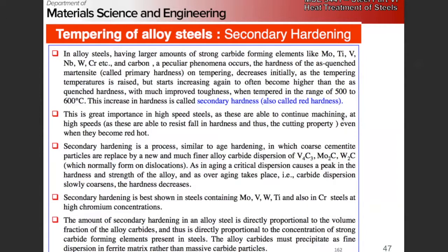So we take austenite, we get martensite? No. When you cool down, all of your austenite is going to change to martensite, provided you miss the nose, right? We hit our critical cooling rate. If we could cool down low enough, we would get all martensite, right? But if our martensite finish temperature is too low, we're still above that at our quench temperature, and we're going to have retained austenite.